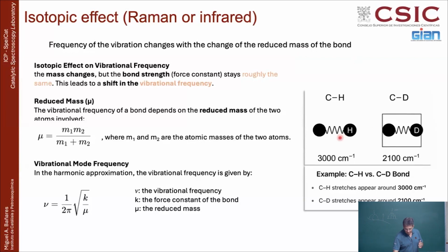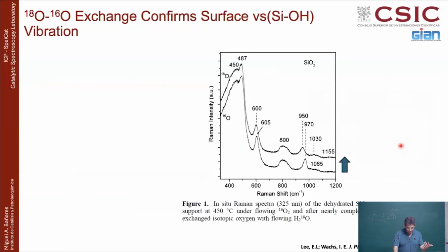Like CH will be vibrating at about 3000 with the same strength. If this hydrogen goes to the deuterium, which is twice as heavy, the frequency change is dramatic, goes from 3000 to 2100. Oxygen 16 to 18, the mass increase is more moderate, but you do see a decrease in the frequency. These vibrational modes are molecular information. These kinds of effects you can see in Raman, but you can see in infrared. So this is also very complementary information that you can get about what is happening. So here, for instance, when the surface is changing the surface hydroxyls between hydrogen and deuterium, you will see a red shift to lower frequency. And of course, the other peaks are the bands from the silica, like here, here, and here.